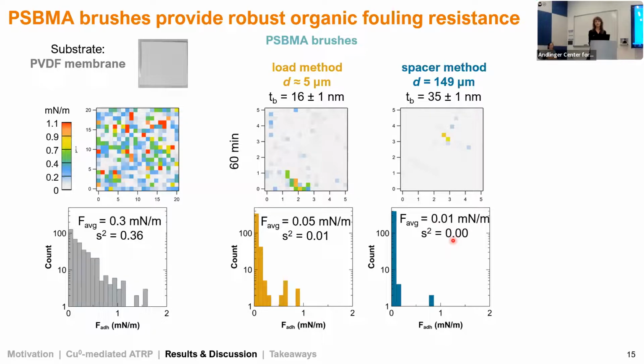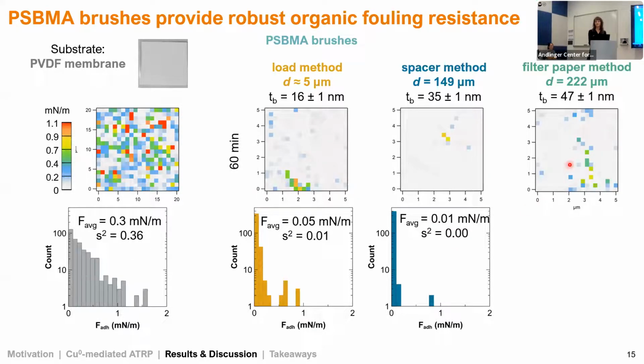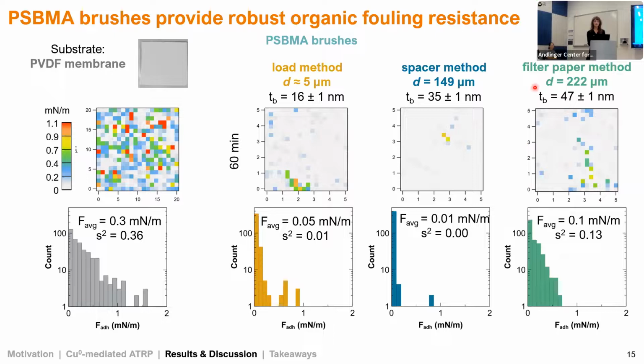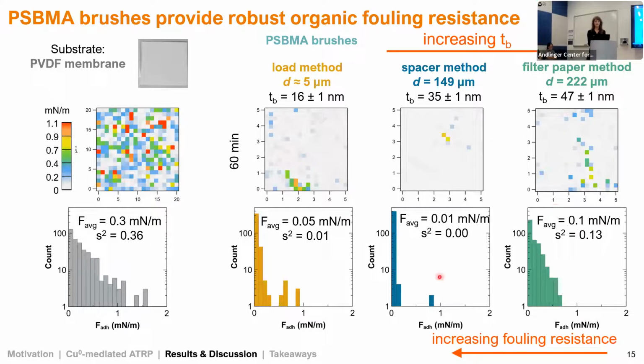Okay, so what about when we go to the filter paper method? We've increased brush thickness here by quite a bit, but we actually haven't improved fouling resistance. In fact, the average adhesion force here is an order of magnitude higher than for the spacer and the load methods, and variance is also much higher. This is especially interesting because previous studies of brush modified membranes have focused almost exclusively on thickness to improve fouling resistance. But we're seeing that with increasing thickness, fouling resistance is actually going the opposite direction.